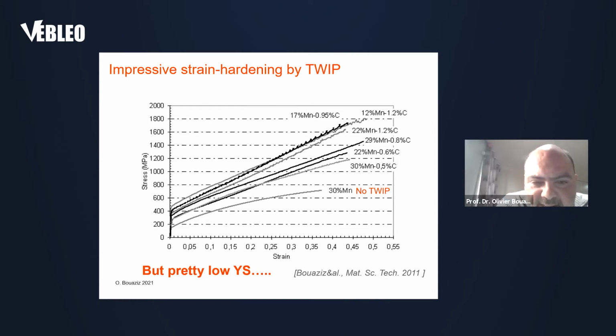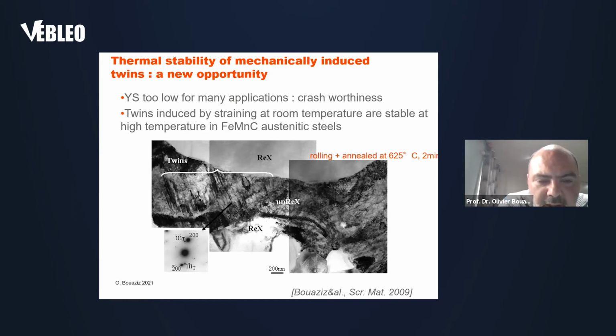The problem with TWIP steel is that despite the high strain hardening, the YS is too low for anti-intrusion applications, for instance. So this picture is a key picture of my talk. It is a TEM micrograph during the recrystallization of TWIP steel. What is interesting to see is that you have a volume fraction of recrystallized material, but in the non-recrystallized material you see twins, mechanically induced at room temperature, persisting at high temperature. So it seems that twins are stable when you increase the temperature.